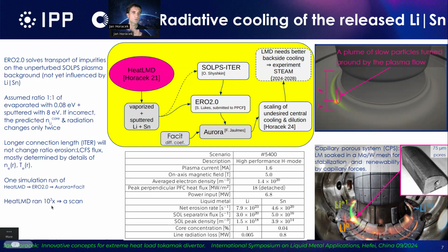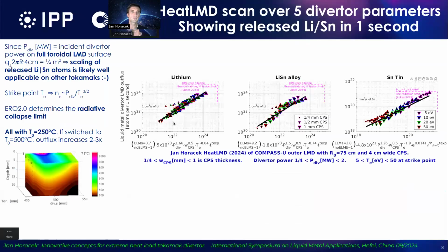The HEAT LMD code can be run not only once, but thousands of times. So I could produce a scaling. It means we are not certain what the plasma will be in our future tokamak. So I vary 5 different divertor parameters, which are the total divertor power on the full toroidal divertor around the tokamak, the thickness of the capillary pore structure, and the electron temperature between 5 and 50 electron volts at the strike point. Then I vary the time over which it's exposed and also the presence of ELMs, yes or no. If they are present, it increases the scaling by a factor of 3.7, or more in this case. And I vary also the alloy. So this is lithium-tin alloy or tin.